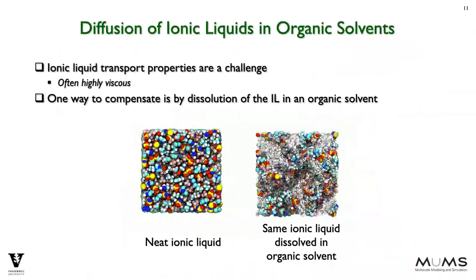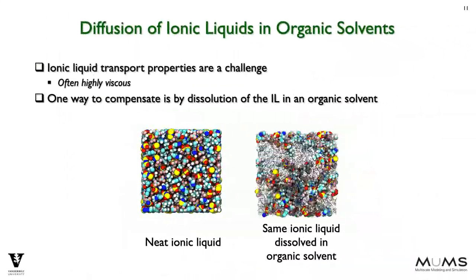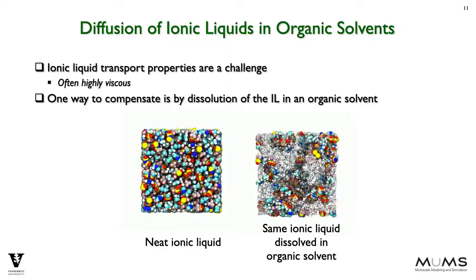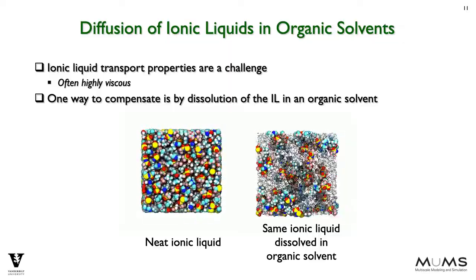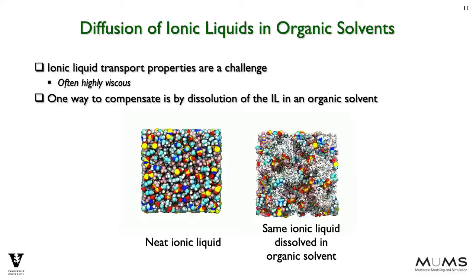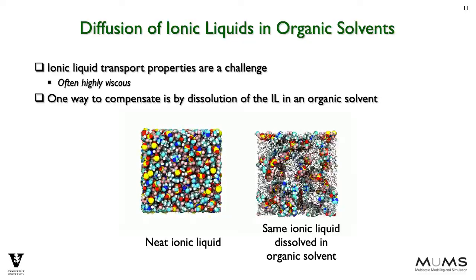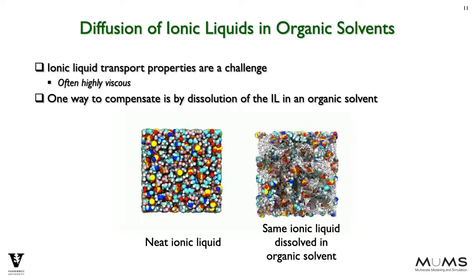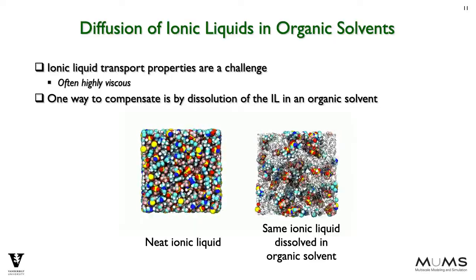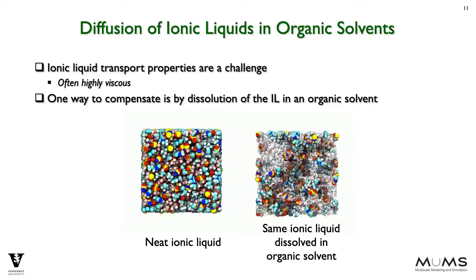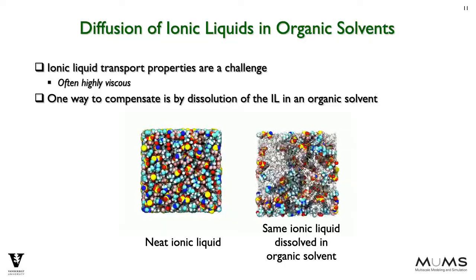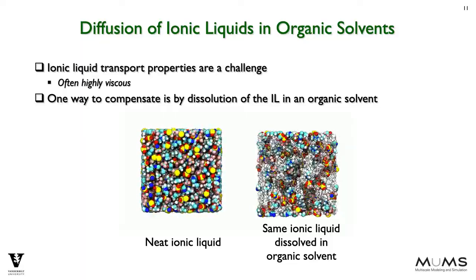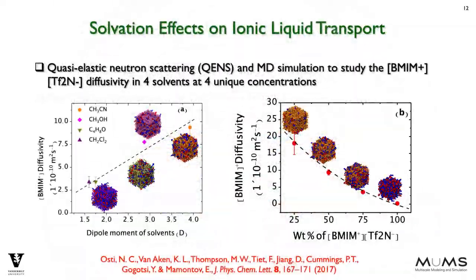As noted earlier, one of the disadvantages of neat room temperature ionic liquids as electrolytes is that they can be quite viscous, and this proves to be a problem as far as transport properties are concerned. One strategy for overcoming this is to dissolve the ionic liquid in an organic solvent. Even qualitatively, it is clear that the ions in the organic solvent, in the video at the right, have much higher mobility or diffusivity than the ions in the neat ionic liquid shown in the video at left. Thus, we have interest in the first center in the use of organic solvents with ionic liquids to improve their transport properties.